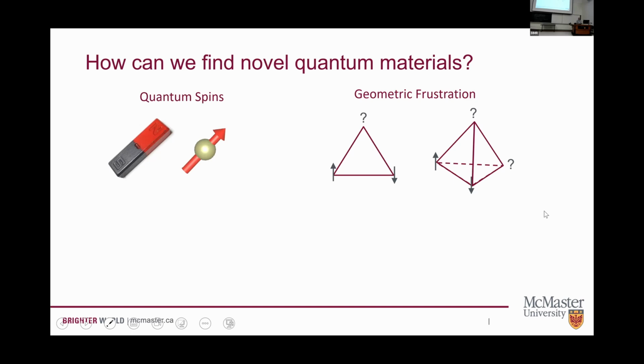Okay, and this is something that we normally show with this classic picture of triangles and tetrahedra. If these magnetic moments here and here want to point in opposite directions, then it doesn't matter which way I put the magnetic moment on the third corner of my triangle, one of these bonds is going to be unsatisfied. Okay, the situation gets even worse. We move from 2 dimensions to 3 dimensions, and now 2 of my 4 spin sites are going to be unsatisfied no matter how I position them.